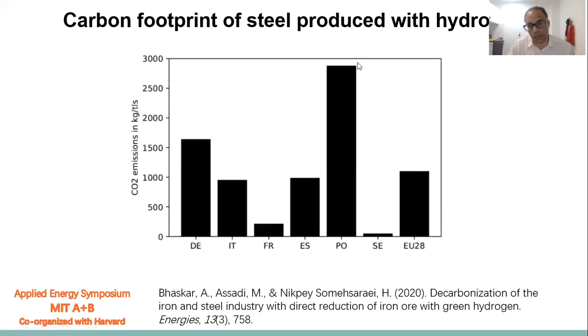So finally, the results of this study performed in Norway show that the average EU carbon dioxide emissions per ton of iron produced are around 1,000 kilograms of CO2. So if we compare with our previous study on biocarbon, the final use of hydrogen could reach a reduction in CO2 emission of 50%. We have to take into consideration that in this study, some of the assumptions are different with respect to our calculation on biocarbon production.